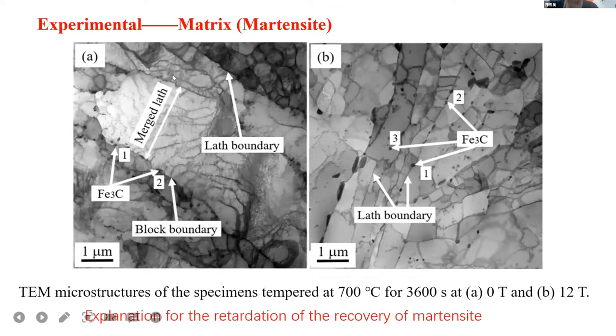Another very interesting phenomenon is about the martensite. Under the magnetic field, we found that the external field retards the recovery of martensite, as in this picture. The martensite is very different from figure A.